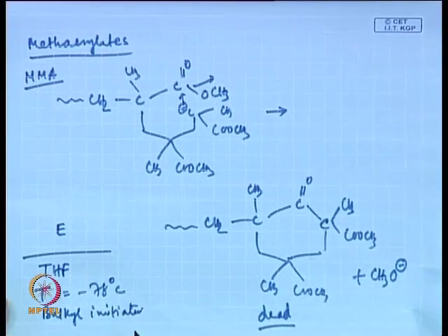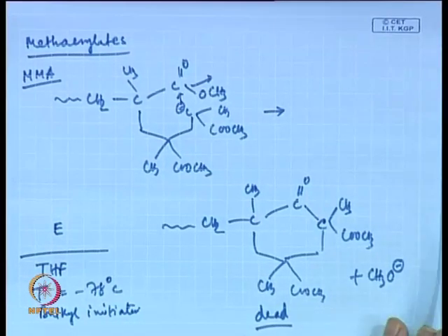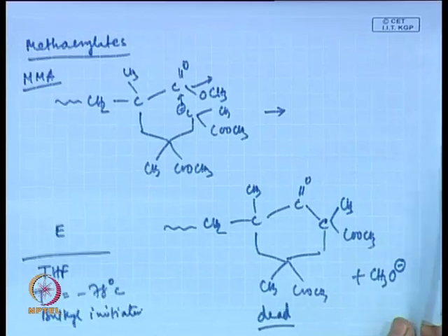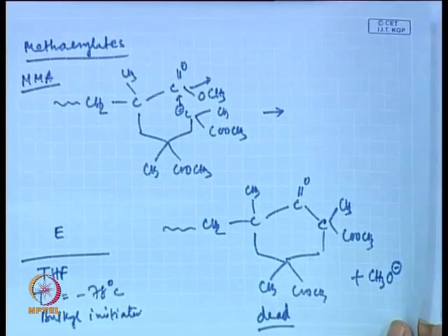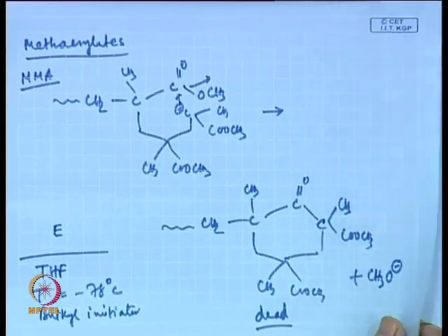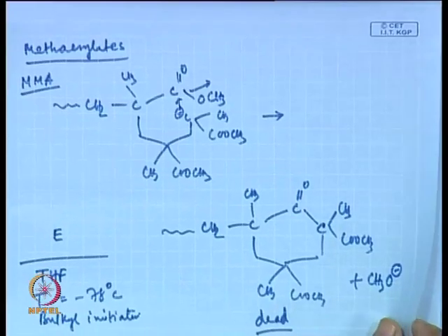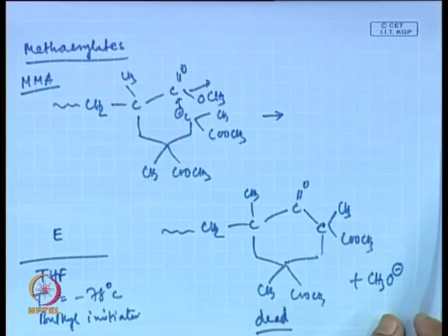So, by using these three strategies you can actually minimize this side reaction for methyl methacrylate and carry out living anionic polymerization for methyl methacrylate, and this similar sort of strategy can be applied for other polar monomers as well. Now, as we have been talking that this anionic polymerization proceeds without termination, but that does not mean that these anionic chain ends live forever.